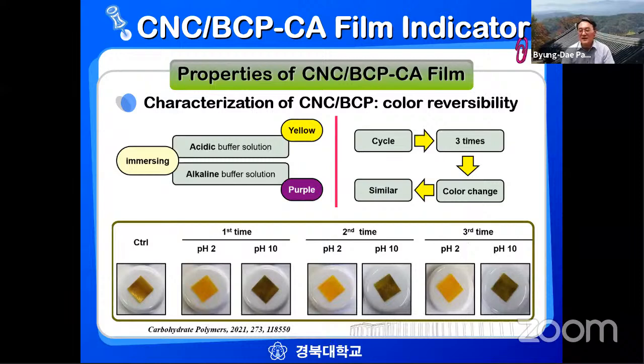And also we check whether the color change is reversible or not. So what we did is we picked pH 2 and pH 10 solutions, and then immersed the film in the solutions 3 times to see whether the color change disappears. We immersed it for 30 minutes at pH 2 and pH 10 the first time, then a second time, and a third time, and there's not much change. That means this color change is reversible. It keeps going up to about 3 times, which means about 1.5 hours.